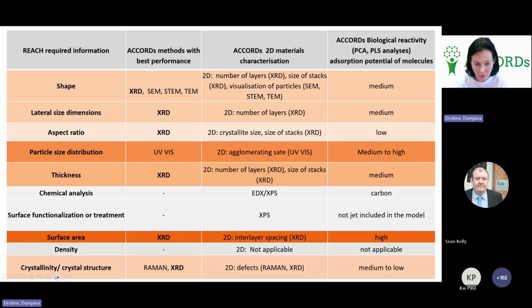Then aspect ratio, it is very difficult to talk about aspect ratio in case of 2D materials, perhaps crystallite size or size of stacks. It's a matter of discussion in the future. Low contribution. Then particle size distribution. We talk about agglomeration, size of agglomerates, which has medium to high contribution to reactivity. Then thickness, it's also difficult to talk about thickness. Perhaps the best would be number of layers, size of stacks.